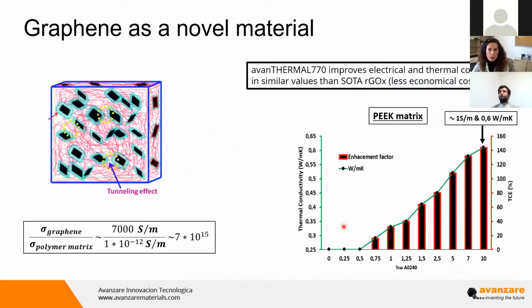So once we have understood these three main features, we are going to see some effects. Apart from the thermal conductivity, I'm going to explain the electrical conductivity, which, as surely you have read and observed in some results, is increasing a lot. For example, in PEEK matrix, we are achieving 15 Siemens per meter in these composites, while the thermal conductivity is more than 0.5 watts per meter Kelvin. This is due to the tunneling effect and the movement of the electrons along the matrix.